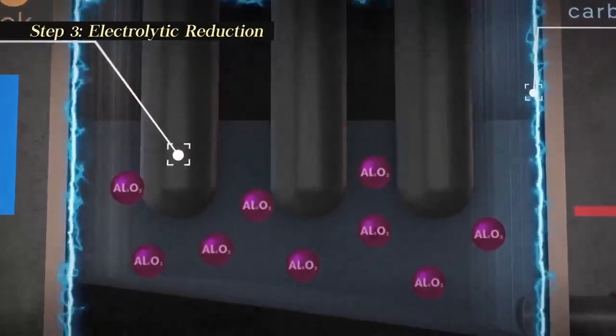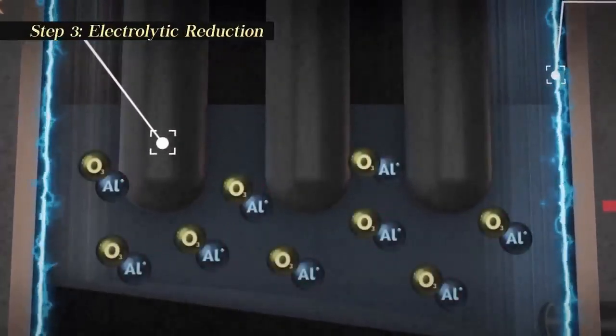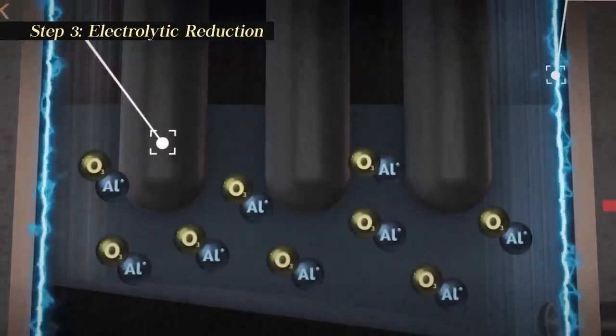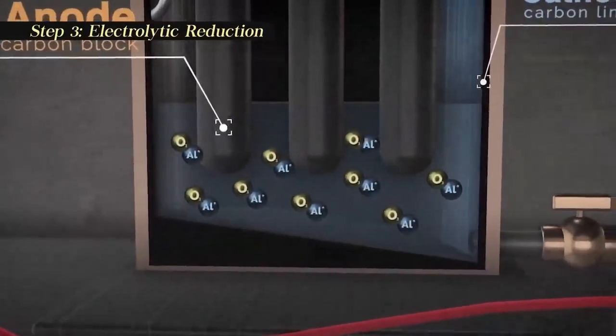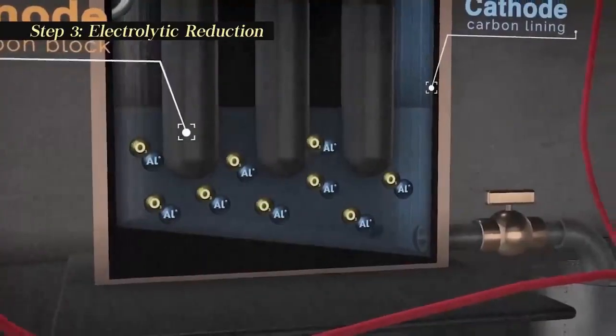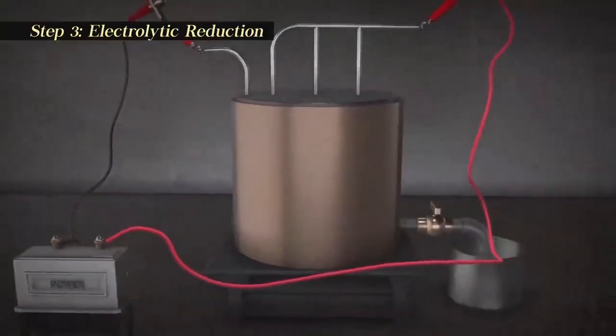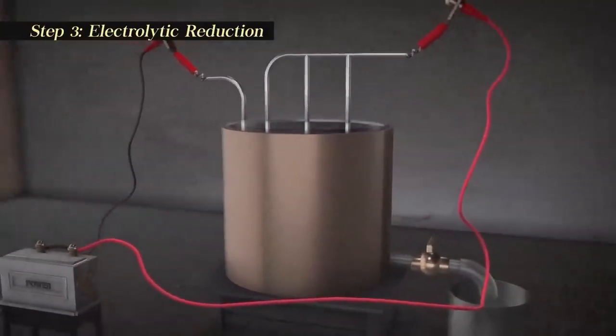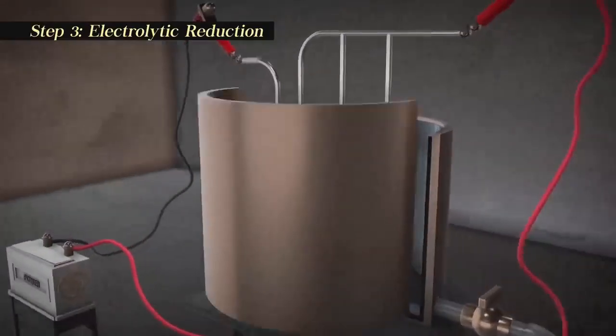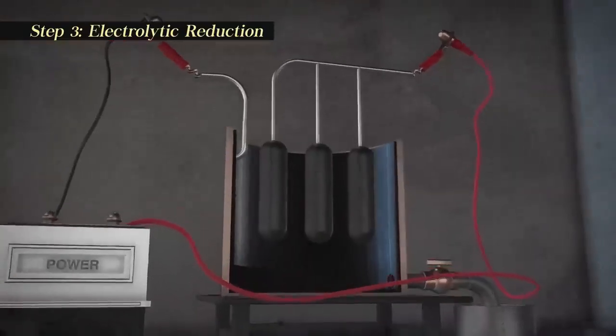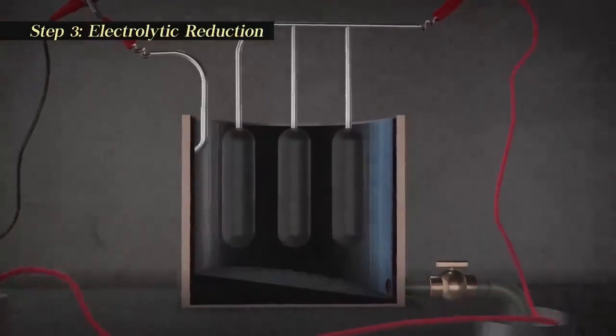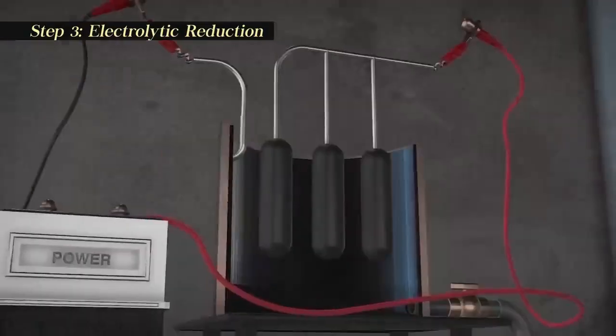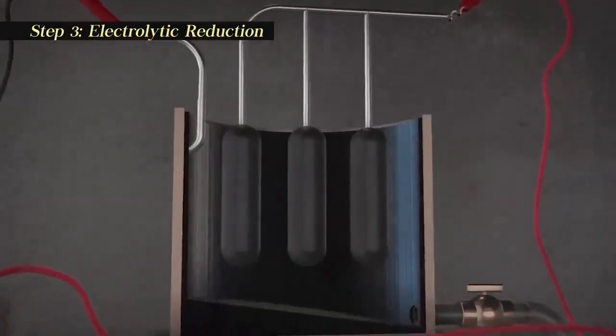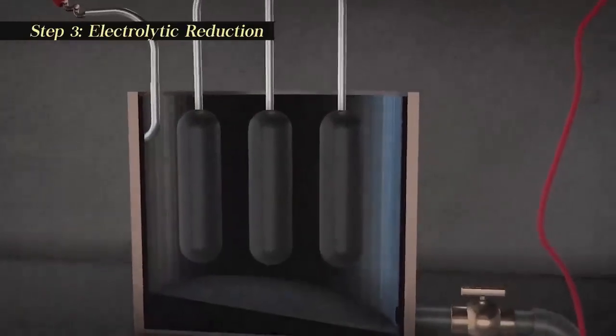To obtain pure aluminum, the bond between aluminum and oxygen in alumina or aluminum oxide must be broken. This is done through the electrolytic reduction of alumina into aluminum metal. This process, called smelting, takes place in a steel vat called a reduction pot. The bottom of the pot is lined with carbon, which acts as one electrode, conductor of electric current, of the system. The opposite electrodes consist of a set of carbon rods suspended above the pot.